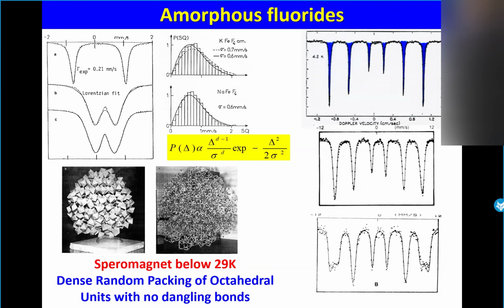And this system was a speromagnet below 29 Kelvin. And the conclusion was to do modeling with dense random packing of octahedral units. On the isomer shift, the value of the amorphous was exactly the same as that for the crystalline phases.